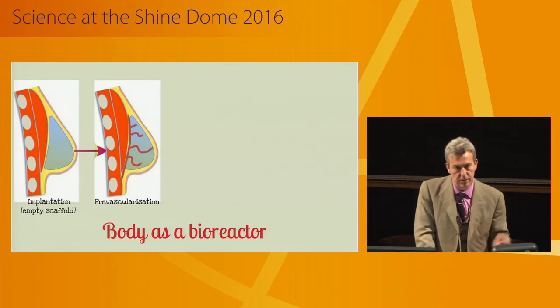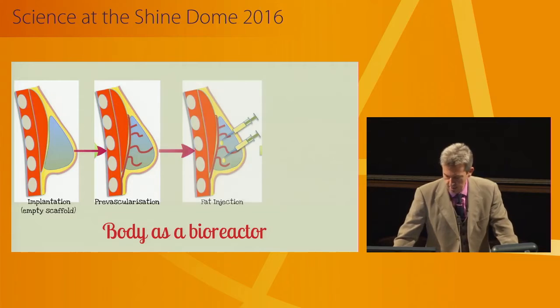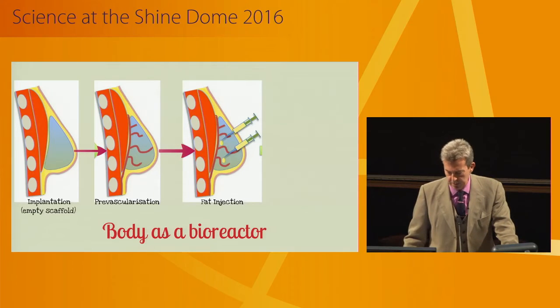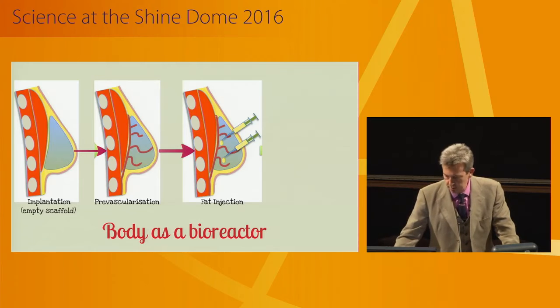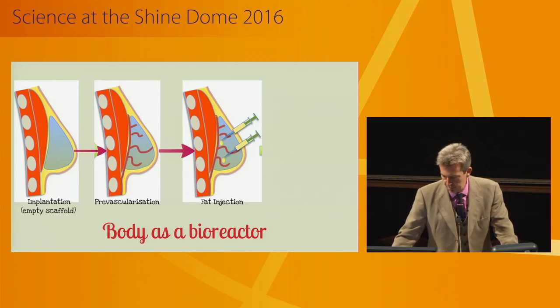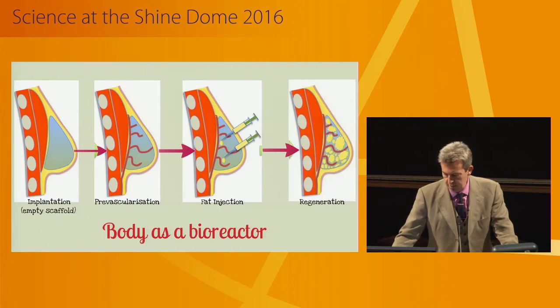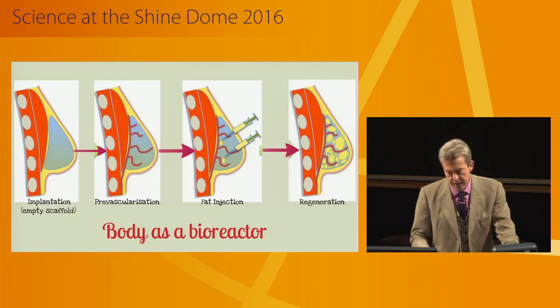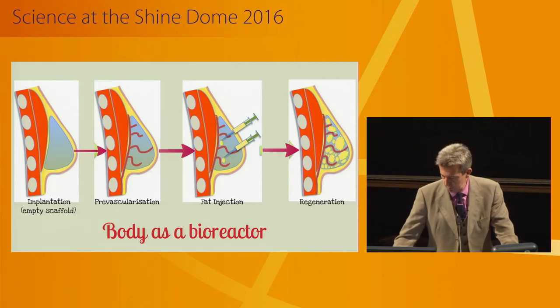So here the rationale is we first implant the scaffold. The vascularization comes after 4 to 6 weeks, and the implant is nicely integrated. Then, in a second minimally invasive procedure, we do the fat transplantation and inject the fat into the scaffold, where the cells from the fat find a vascular bed, have a much higher chance of survival, and therefore remodeling. And then complete regeneration, because we are using biodegradable polymers, which have been used in the clinic for many years for sutures, plates and screws and so on.